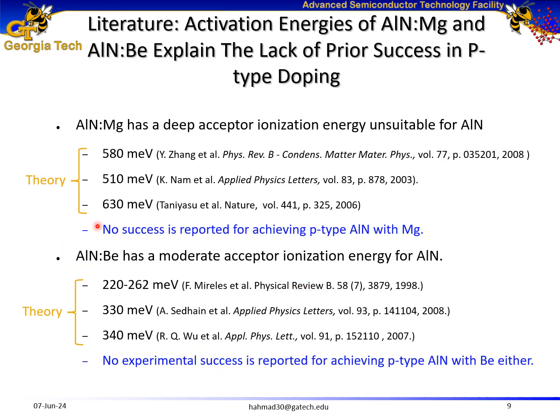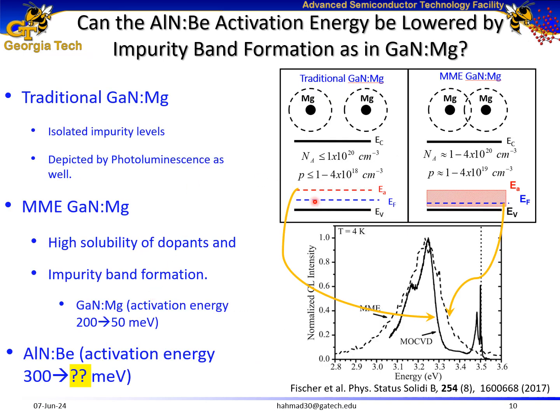Generally, the theory agrees that the activation energy of beryllium is lower as compared to the activation energy of magnesium in aluminum nitride. The activation energy of beryllium in aluminum nitride is found to be approximately 300 milli-electron volts. In traditionally grown magnesium-doped gallium nitride, we find isolated impurity levels, which is also depicted by its 2 peaks in photoluminescence measurements. Now, on the contrary, in metal modulated epitaxy, we can achieve high solubility, and also we achieve impurity band formation overlapping the valence band of the semiconductor, which is also depicted by a single photoluminescence peak where the band overlaps that of the gallium nitride 3.4 electron volts band gap.